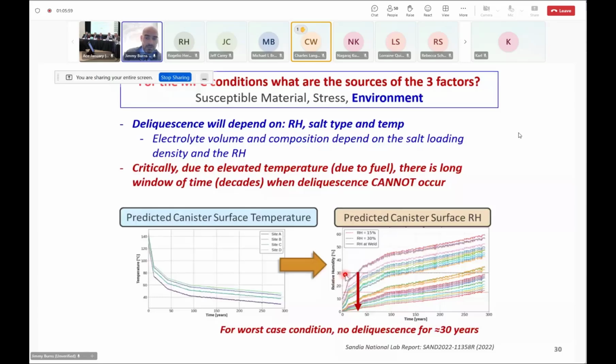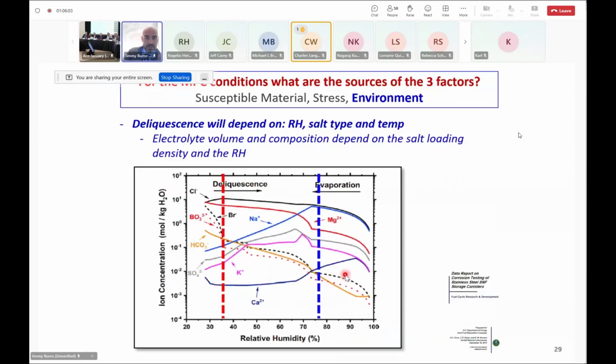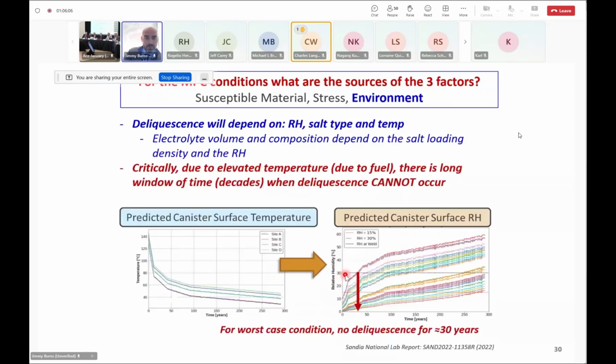Well, let's just say you need a relative humidity of 30% for this deliquescence process to happen, right? So remember, we talked about the deliquescence. You need a certain level of humidity based on the salt type. Let's say you need a 30% relative humidity. So in this instance, in order to get there, it's going to take a significant amount of time, right? So the worst case in this example, there'd be no deliquescence on the order of 30 years, simply because the canister surface temperature is too high to thermodynamically support that electrolyte.